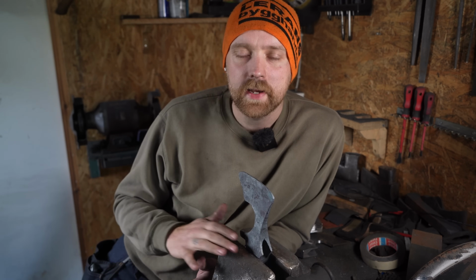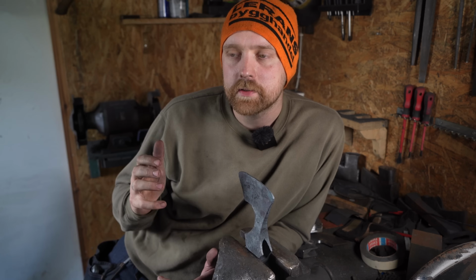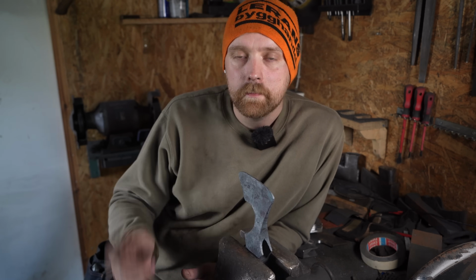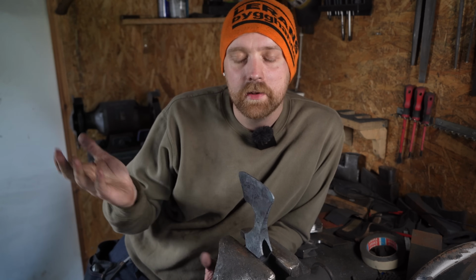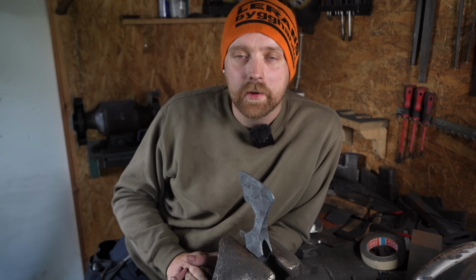And don't be discouraged if you have a delamination, okay? I have friends that are master blacksmiths that every batch have to put 1 or 2 axes aside because of delamination. And that happens to me too all the time, so don't be discouraged. And there can be multiple reasons as to why. Usually it's because you didn't pay attention, maybe you didn't have enough heat, maybe you didn't clean it properly, maybe your hammering was a bit off and something got in. It can really be a lot of things, but usually it wasn't clean enough and not hot enough. That's usually the answer, but there can be other answers as well. So don't be discouraged, get back up on that horse and try again.